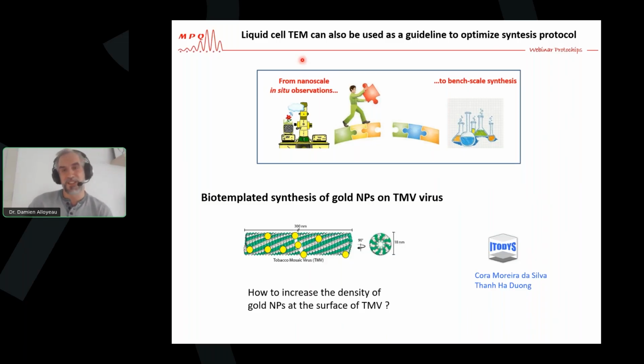What I wanted to show you with this study was that liquid cell TEM can be used as a guideline to optimize the synthesis protocols, exactly as we did with the in-situ heating experiment on the nanoalloy systems. We worked in collaboration with the ITODYS laboratory in the chemistry department of the University Paris Cité. We worked on the biotemplated synthesis of gold nanoparticles on tobacco mosaic viruses. And what we wanted was to optimize the optical properties of those nanoparticles. We wanted very large plasmonic absorption bands for those nanoparticles.